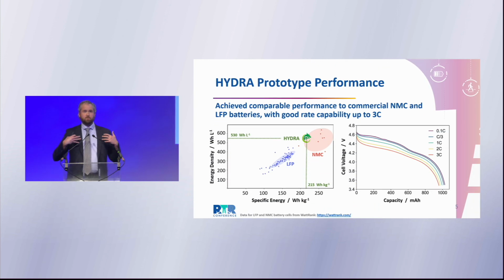So we've been able to improve the sustainability of the battery. We've been able to improve the cost. But how does it perform? What are its performance metrics? We can see that summarized in this slide, where on the left we see the specific energy and energy density of traditional chemistries like LFP in blue and NMC in red. And our Hydra technology lies in between those two. So it's a cobalt-free material like LFP, but it's still able to achieve relatively high energy density and specific energy like NMC. So trying again to balance the benefits of these two methods.